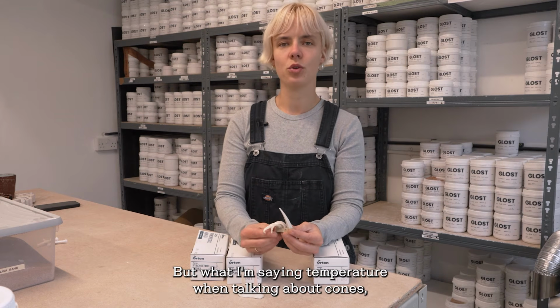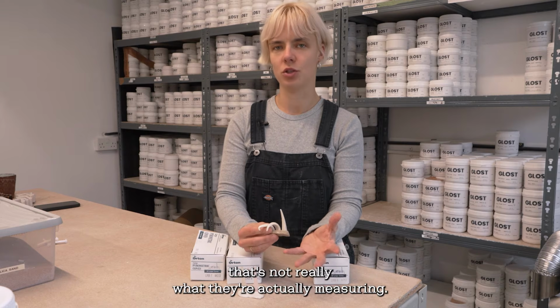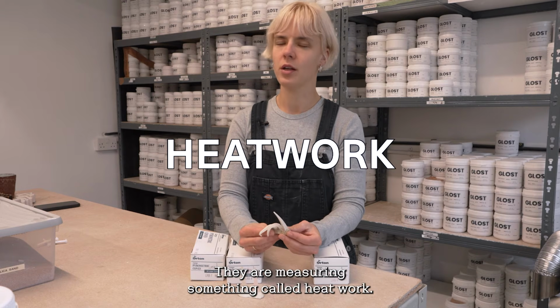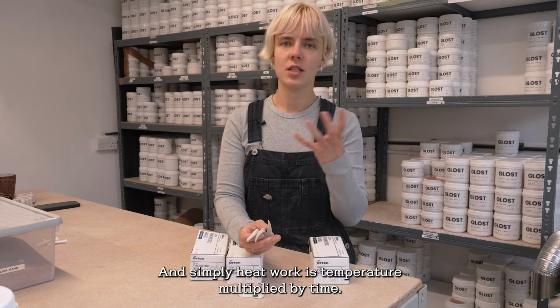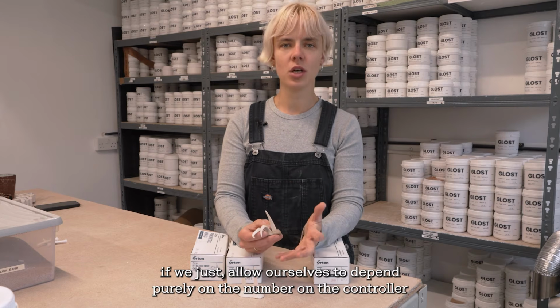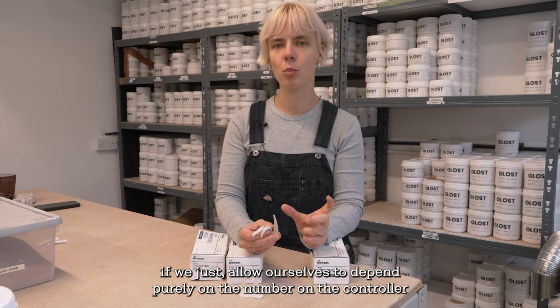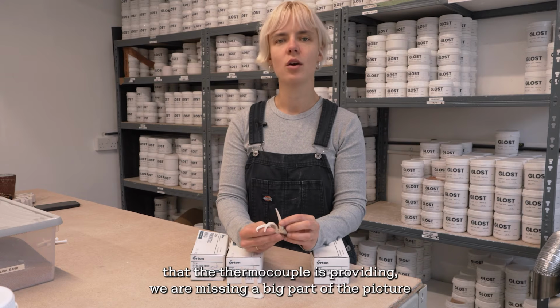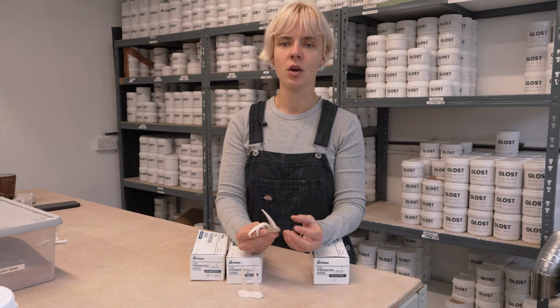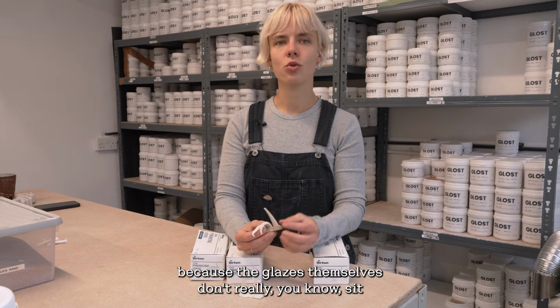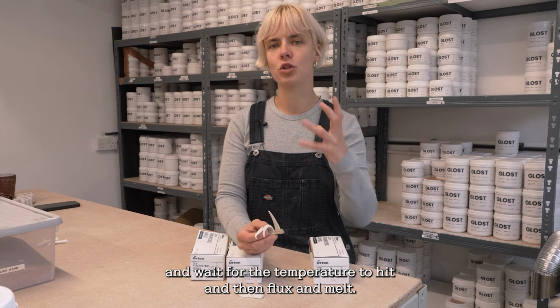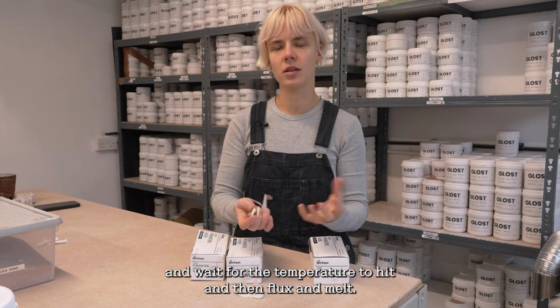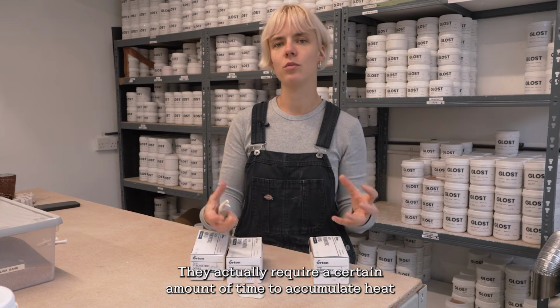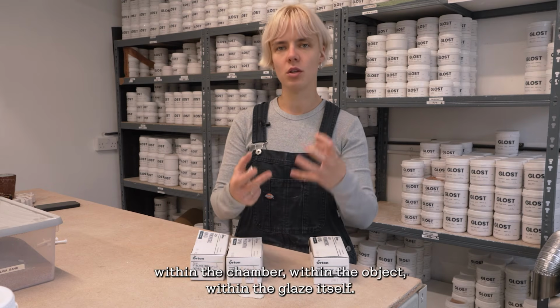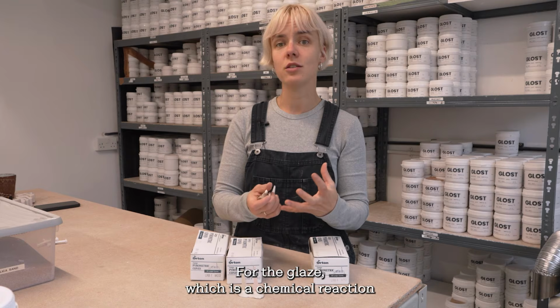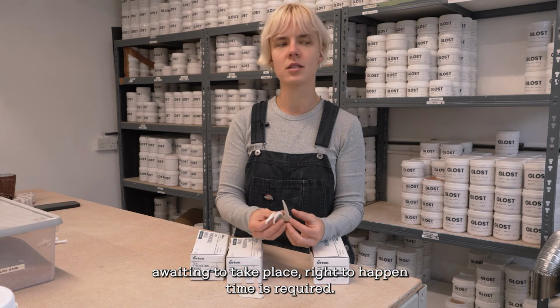But whilst I'm saying temperature when talking about cones, that's not really what they're actually measuring. They are measuring something called heat work. And simply, heat work is temperature multiplied by time. If we just allow ourselves to depend purely on the number on the controller that the thermocouple is providing, we are missing a big part of the picture, because the glazes themselves don't really sit and wait for the temperature to hit and then flux and melt. They actually require a certain amount of time to accumulate heat within the chamber, within the object, within the glaze itself, for the glaze, which is a chemical reaction waiting to take place, to happen.